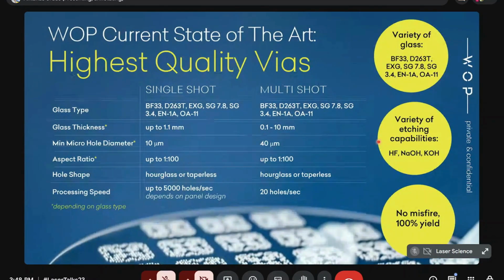So we got, I think it was at the show in Taiwan, people said that our vias are the best quality. They say, we believe. So you can see quite a big variety of glasses we work with, and all of them are considered very good candidates for glass core in the semiconductor industry. These vias were etched in alkali etchants and in acid etchants, and what is important, we can ensure that no bad vias appear across all the working area.